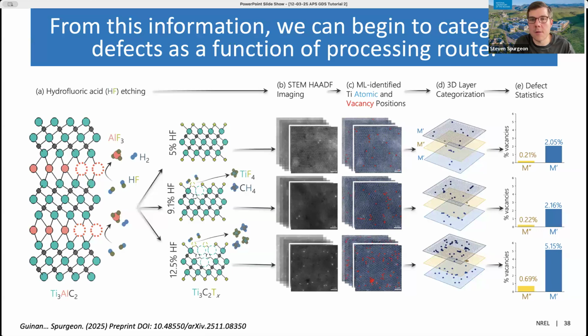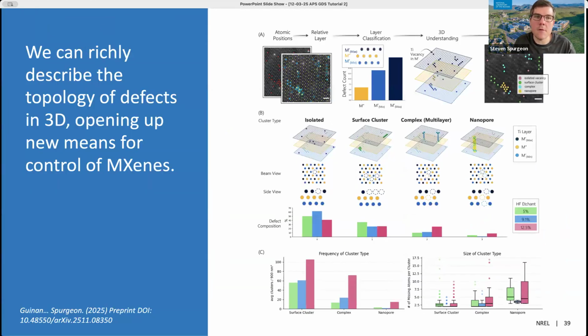This is something that would not be possible with manual analysis. It would not be possible with the 2D Gaussian approach because of the brittleness of the approach. So this allows us then to really describe the defect topology in these materials. We can start to evaluate where defects are isolated, how they cluster together, whether they form complex interlayer structures, even pores in the material.